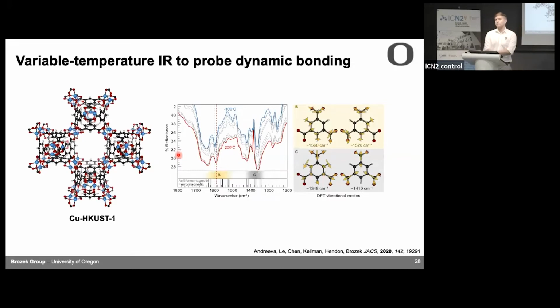So we picked about 20 of the most common MOFs. I'm going to focus mostly on copper BTC, but we picked the 20 most common MOFs, and we measured their IR spectra as a function of temperature. That's what this looks like. And they redshift. Turns out a lot of these vibrational bands redshift. We were thinking this is probably the asymmetric, this is the symmetric. They redshifted, but so did a bunch of other bands. And so I wanted to know what were all these bands that were redshifting. And so we worked with my collaborator, Chris Hendon, who's a computational chemist. And he helped us assign these bands.